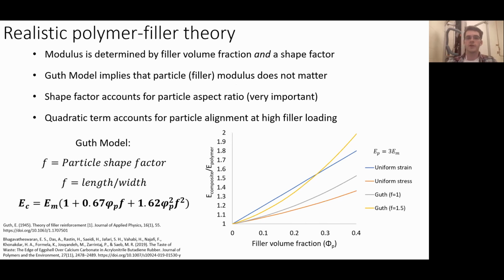So in the 1940s, Dr. Guth actually developed a much more realistic model of Young's modulus based on filler volume fraction. And this incorporates something called the particle shape factor, which is essentially your particle aspect ratio, which tells you how much surface area of your particle itself is interacting with your polymer matrix. And so the higher the shape factor is, the faster your composite modulus is going to increase.